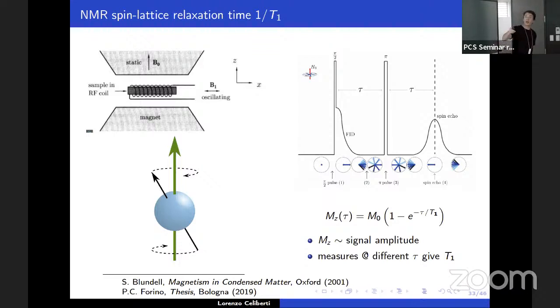What has been done is saturation recovery measurements, where you first apply a pulse and the spins are flipped onto the plane, then they start to dephase, so you don't see anything. After a delay time tau, you apply another pulse so that the spins change directions on the plane, and then after another time tau they are again in phase, and you observe this signal here. The amplitude of this signal is proportional to the magnetization along the z-axis of the sample.